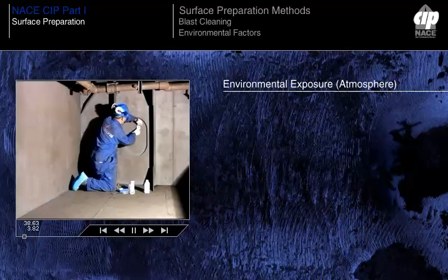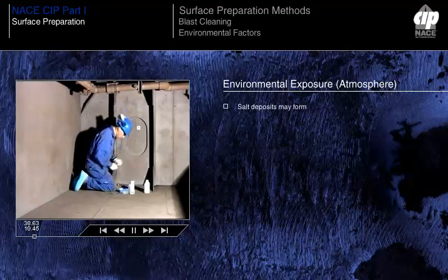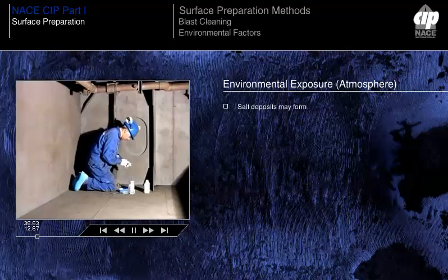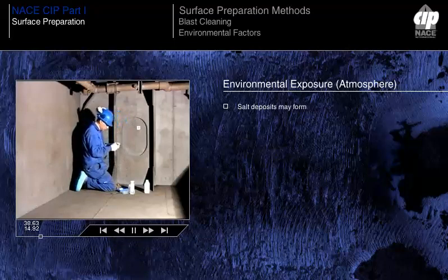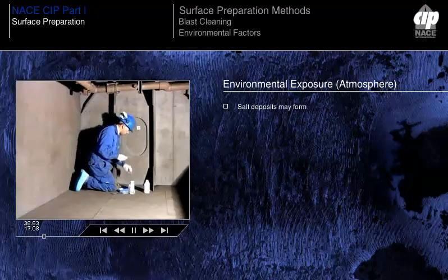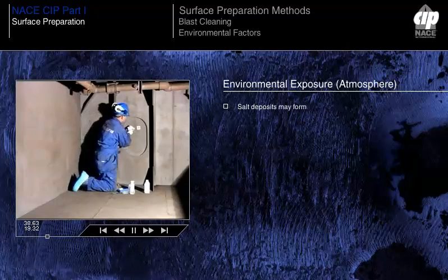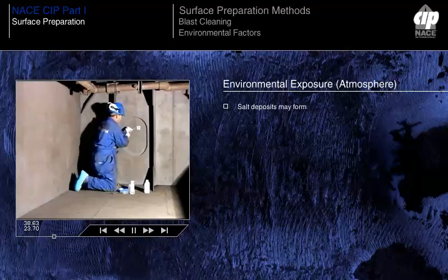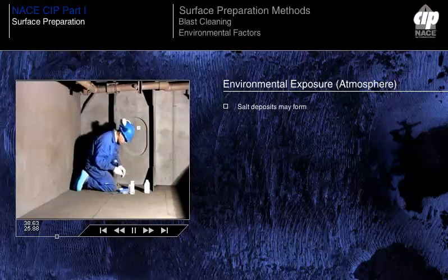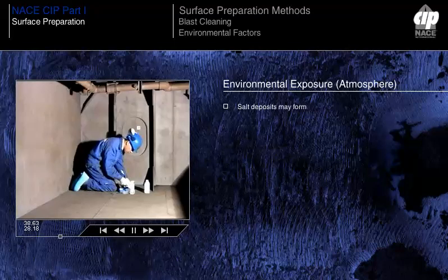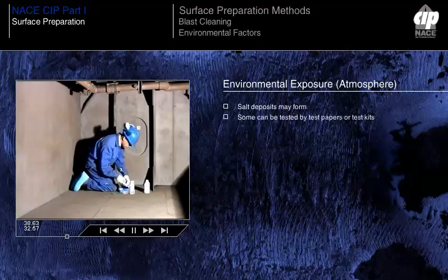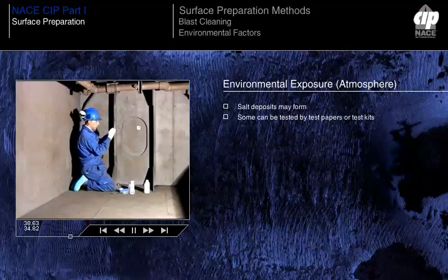In marine and industrial environments, where the air contains particles of chemical salts, the possibility exists that these salts may deposit on the workpiece. If this occurs after blast cleaning but before coating, it may be necessary to wash and re-blast the surface. The presence of certain chemical salt deposits, such as ferrous sulfate or ferrous hydroxides, may be determined by means of test papers or chemical test kits.